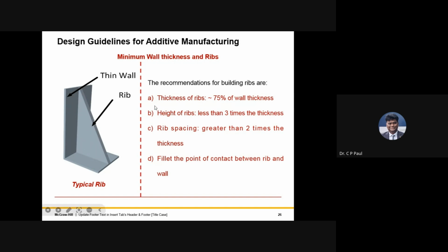The thickness of the ribs is normally 75% of the wall thickness, and the height of the rib has to be less than 3 times the thickness. Rib spacing has to be greater than 2 times the thickness, and the fillet at the point of contact between the rib and wall decides on many of the parameters. So this is how minimum wall thickness and the ribs are built in general in plastic as well as in metal additive manufacturing.